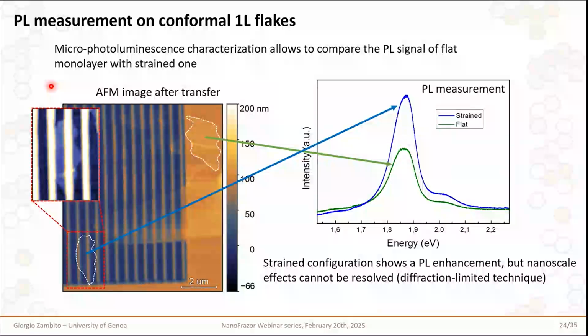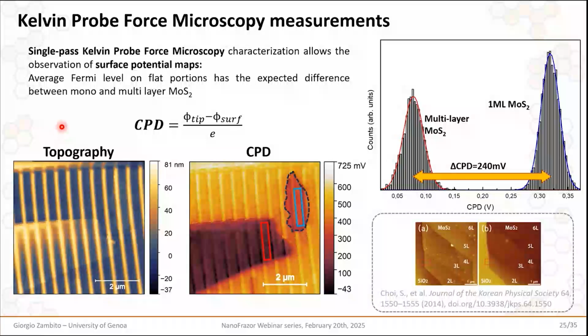However, the effects that we expect to observe are likely to be present at a higher resolution scale, since we are using and exploiting patterns that have sub-micrometer periodicities, and hence a micro-Raman spectroscopy like this is not suitable because it is diffraction limited and does not allow us to observe these kinds of very fine effects. So to overcome this limitation, we relied on Kelvin probe force microscopy measurements.